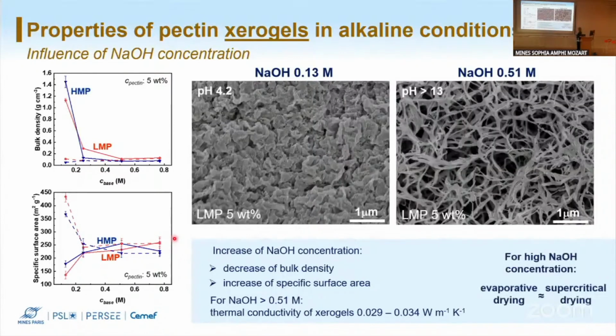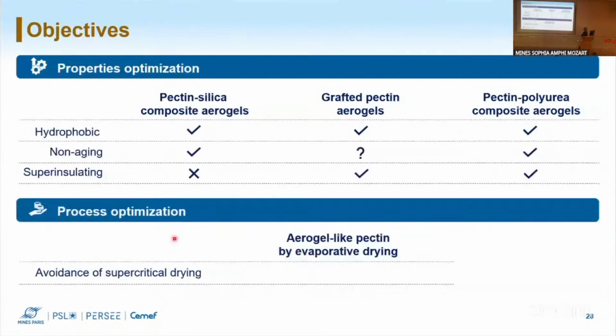Most importantly, the most important fact was that when we had a high concentration of base, we could obtain the same materials by evaporation as we could by supercritical drying. So coming back to our objectives for the last time, working on the process optimization in order to avoid supercritical drying, we made the aerogel-like pectin by coagulation in alkaline media. And we could achieve avoidance of supercritical drying. However, still we do not have super insulating materials.